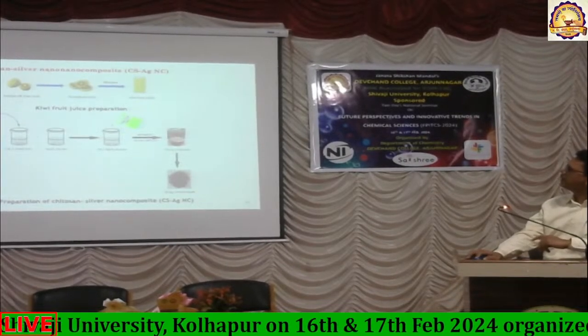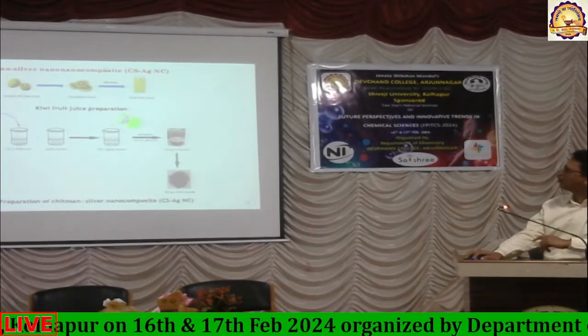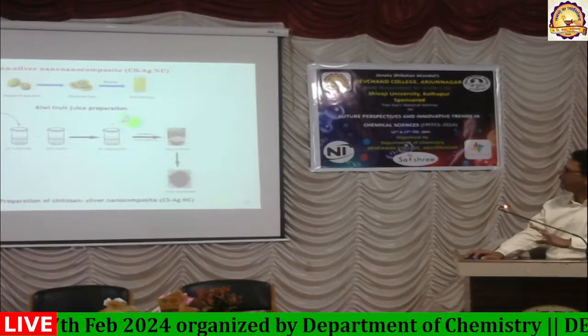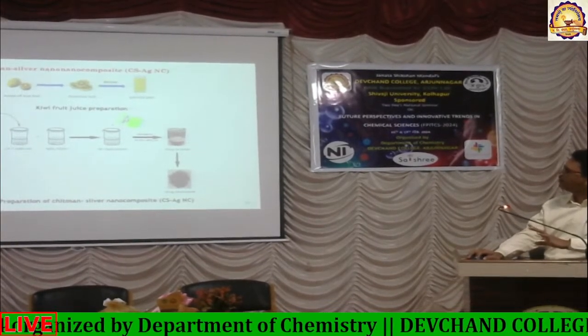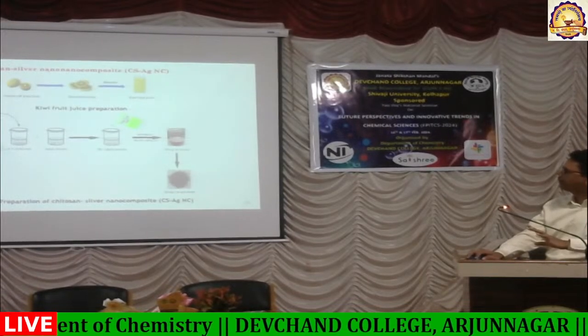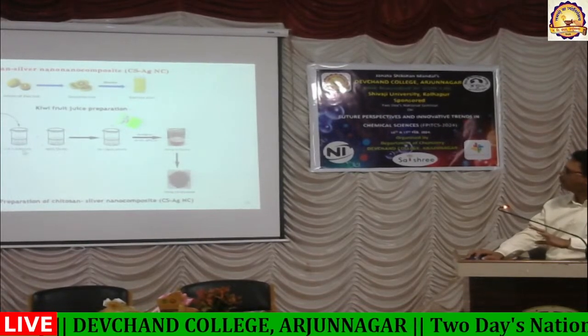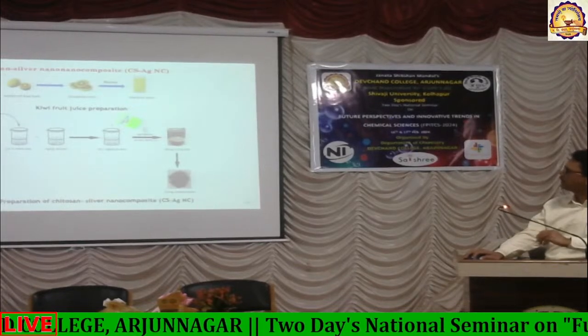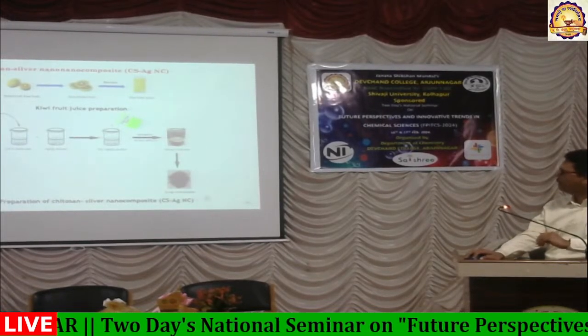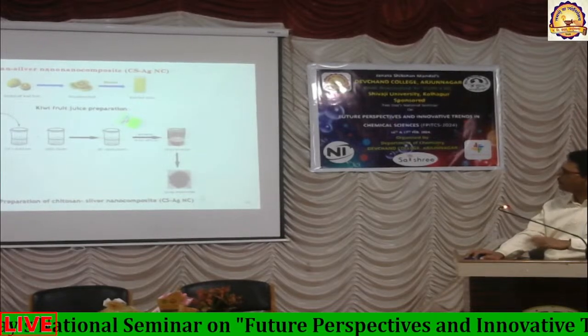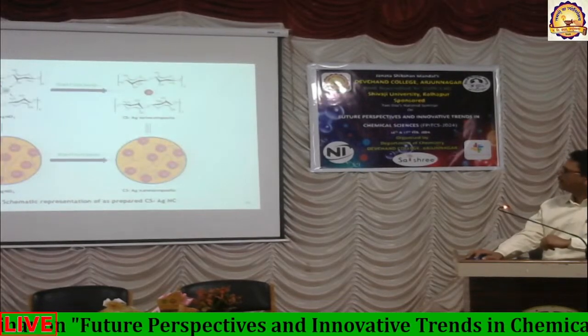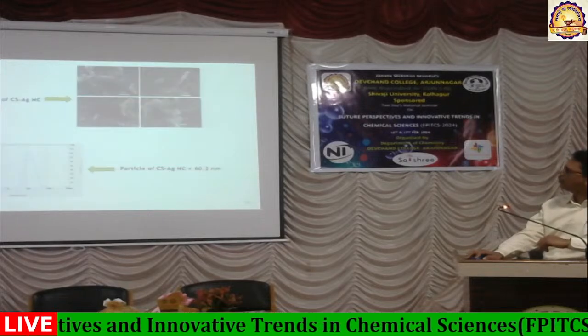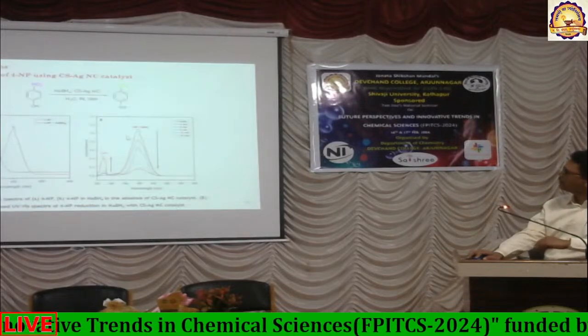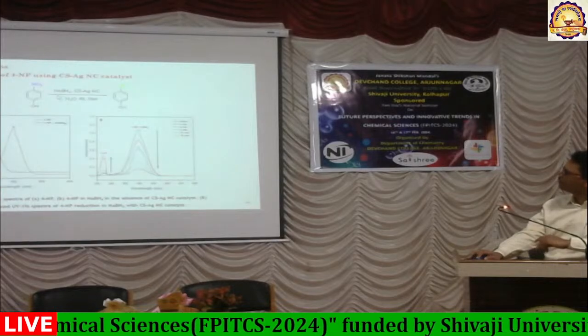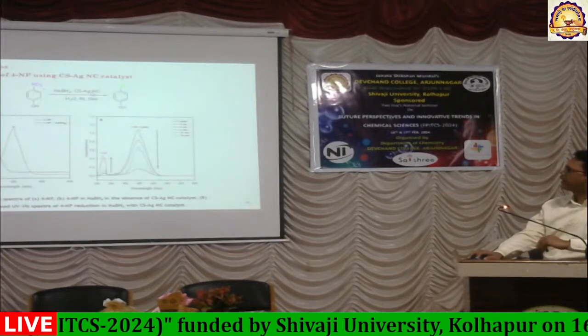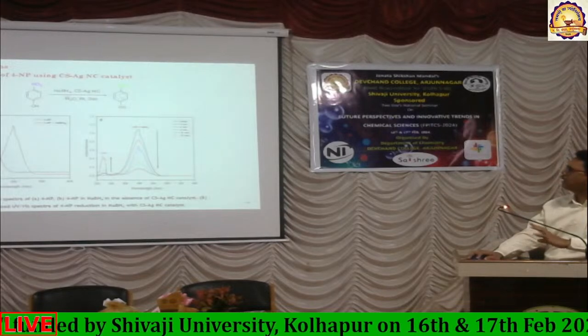So this is also another example of a chitosan silver nanocomposite, where the same kind of strategy was used. Instead, we made use of a mixture of chitosan and acetic acid, and a mixture of all these three was taken, and through that we got a chitosan silver nanocomposite, and this was used. This is a schematic representation, and this is of course a SEM image. It was used as a reducing agent in the presence of sodium borohydride, which of course acts as a reducing agent, and it catalyzes the reduction.